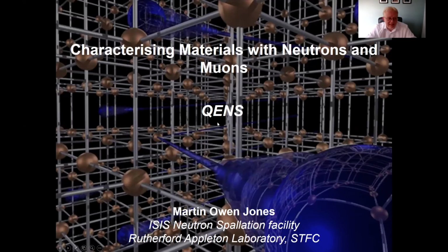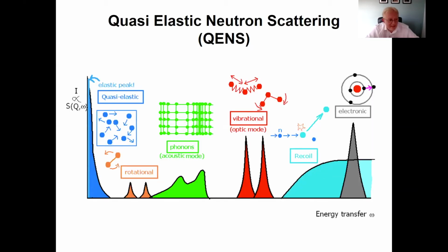QENS is quasi-elastic neutron scattering. It's very like inelastic neutron scattering, except all we're looking for is the scattering that's very close to the pure elastic line. So essentially what we're looking at is the broadening of the elastic line, and that broadening is caused by motion of species within the solid.